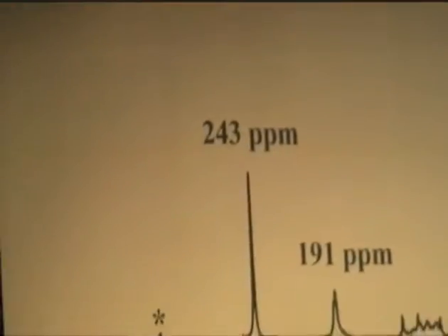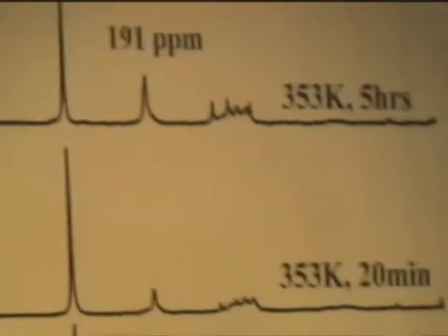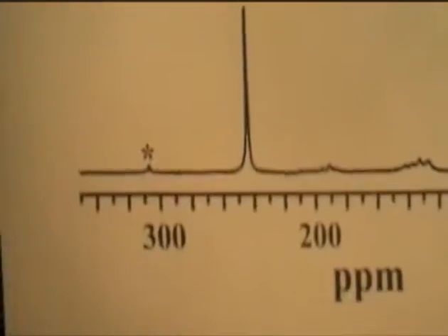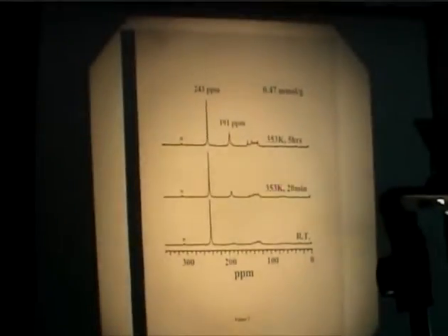Now what you do, he worked with zeolites, and what he did is he took the 100% sulfuric acid, 90% sulfuric acid, and he allowed a little acetone into it, with the carbonyl carbon 98% carbon-13, so he could get a nice spectrum easily. And he looked at what happened. And then he did it with the zeolites.